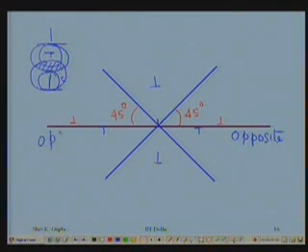Here opposite sign attract. Here is the same sign. Here also the same sign. So the whole region in the crystal around a straight dislocation line is divided into 4 segments, by the slip plane and planes making an angle of 45 degrees, another plane here, another plane there.